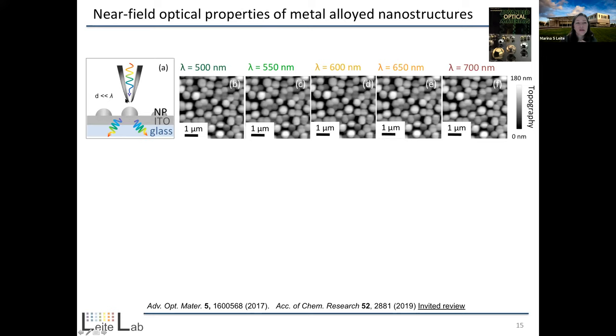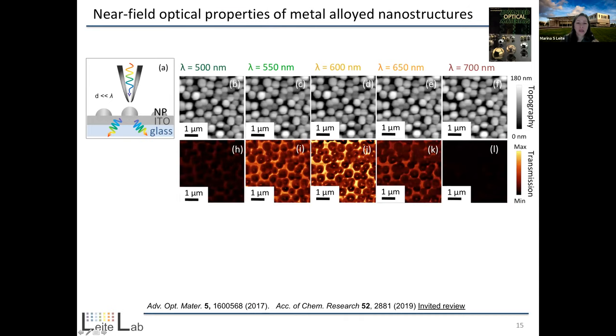As we raster scan, we acquire information about the morphology. Here you're seeing very repetitive data, showing that as we change the wavelength of this excitation light, nothing changes significantly in the topography. That's good. Then in this row, what you're seeing is a scan that results from all the light being transmitted, captured by an objective lens underneath our sample.